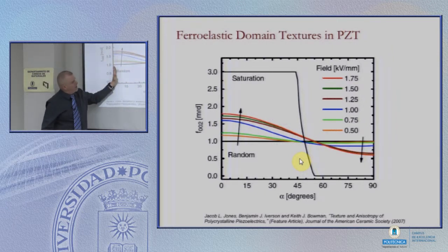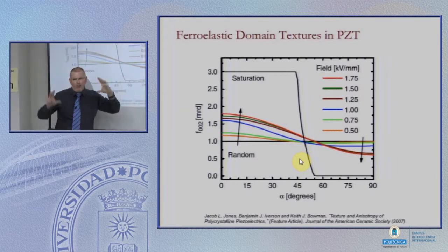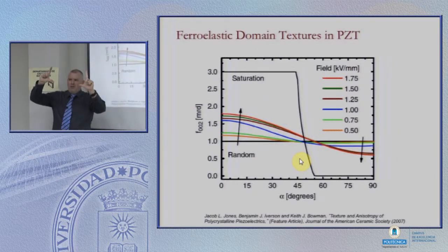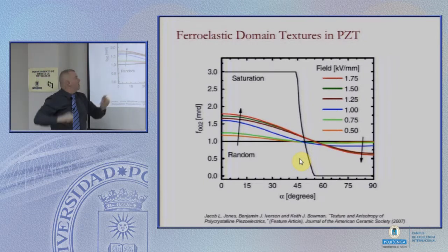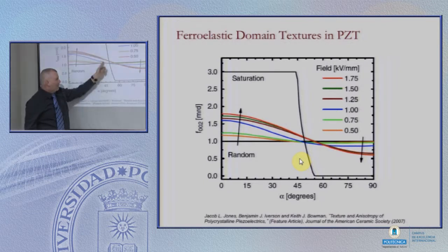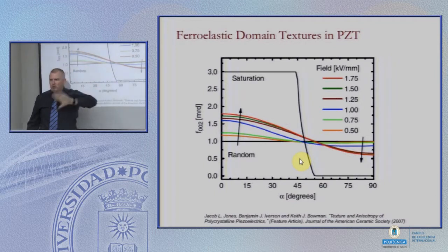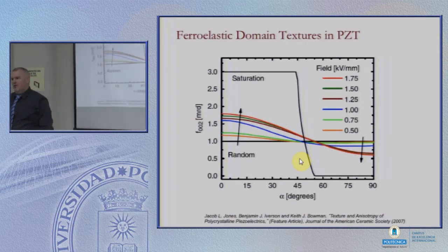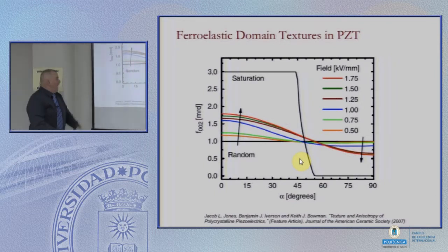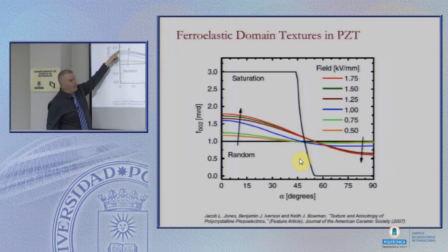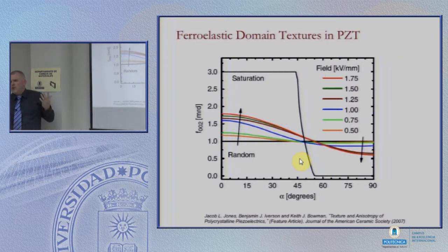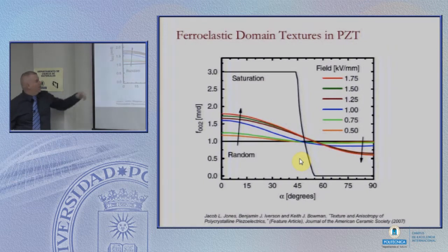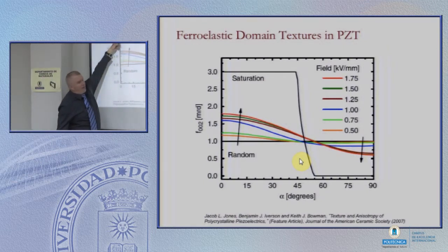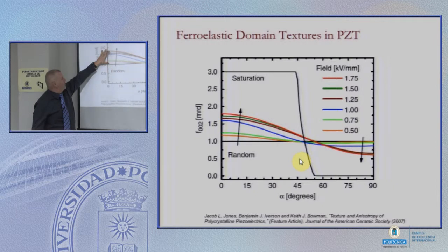What this plot does is it shows the relationship for crystals at this orientation, all the way to 90 degrees. Right? So we actually go through the whole process. This is theoretically what's possible if all of the grains moved, if those domains moved in the favorable direction for all of them. And this is what we actually get in a commercial material. And so the question is, the potential of the material is up to here, right? But in this polycrystalline material, we only get a much lower value.